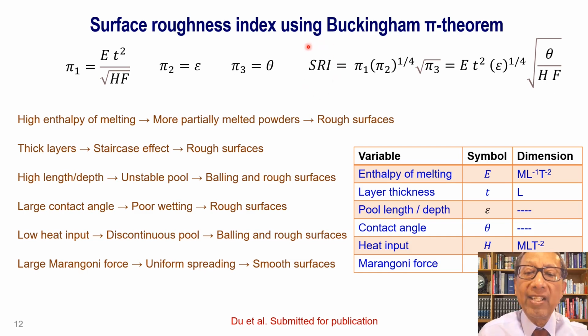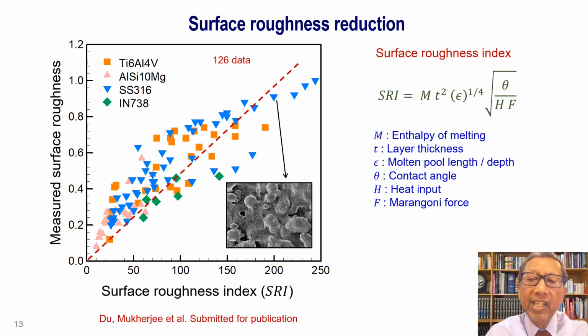And we can plot the SRI as a function of experimental data on these variables so that the model can be validated. Here we compare the computed surface roughness with the corresponding measured experimental values, and they seem to show a fair agreement with 126 independent experimental data. And these types of models, when they are validated, can be used to reduce roughness.